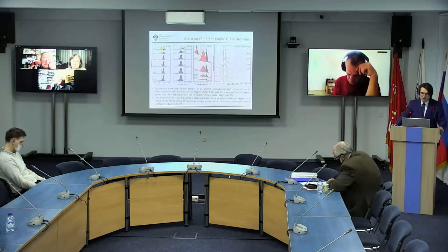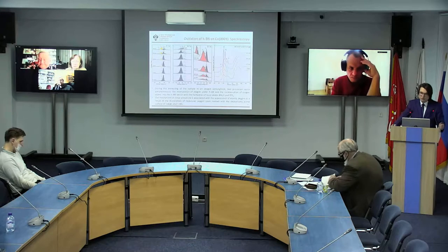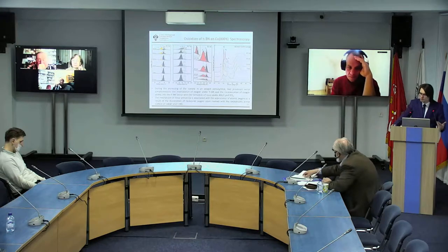So let's shift to the next part of our results, namely the oxidation of a monolayer of hexagonal boron nitride on cobalt. Let's start with the interaction with the cobalt substrate. Long heating in oxygen demonstrated that during the oxidation of hBN on cobalt, we see the formation of two types of local active structures, BN2O and BO3, with atoms of oxygen surrounding boron.